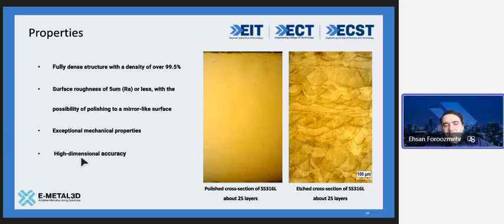Exceptional mechanical properties is another feature. I will show that in the next slide. And also high dimensional accuracy. We are talking about 50 micron plus or minus accuracy, which is good enough for many applications. But obviously, when you're talking about fitting surfaces and also high tolerances, we need to expect some post-processing like machining or grinding to happen. But the as-printed part is good enough for many applications.